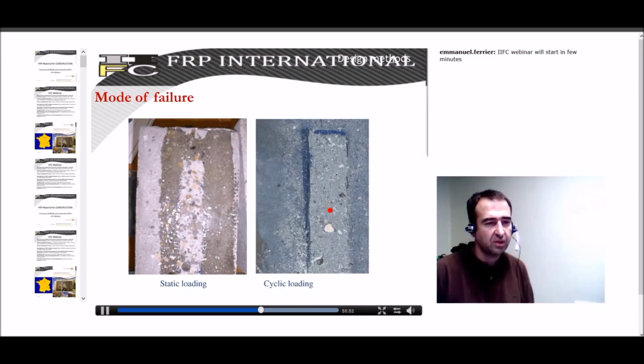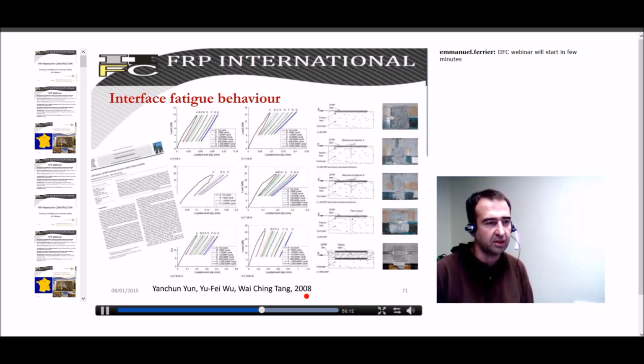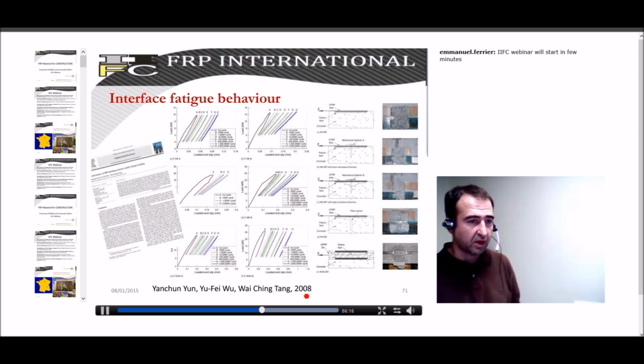What we observe is that we have some decrease in properties in the adhesive because the failure mode changes from a cohesive to a non-cohesive failure. For this, it was very interesting for us to see the mechanical decrease and the fatigue. Since then, there have been, of course, other studies done.